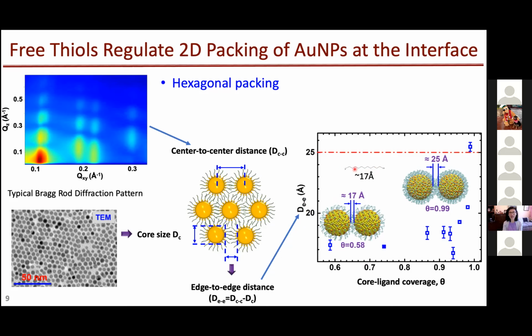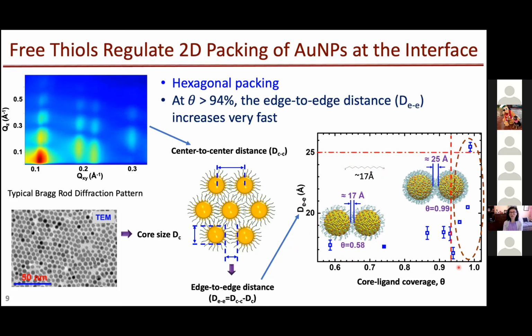We can see that below 94% coverage, the spacing between the particles increases gradually. However, above 94%, the distance increases quite fast. That distance I already mentioned corresponds to this 94% where we describe the elastic property of the films.